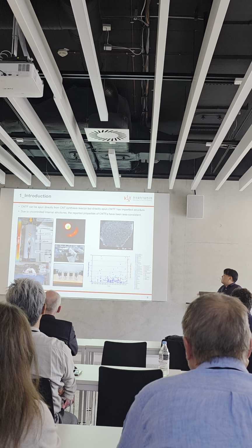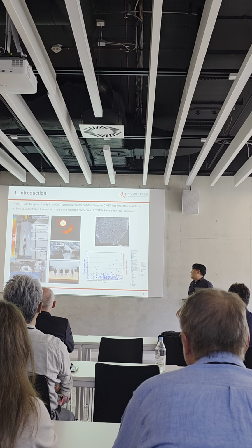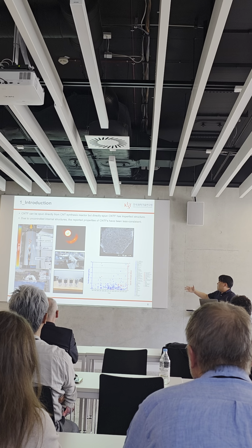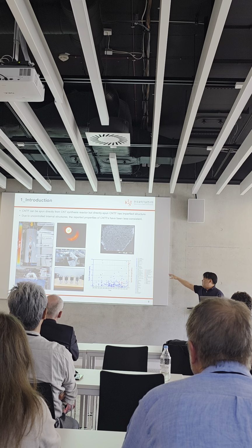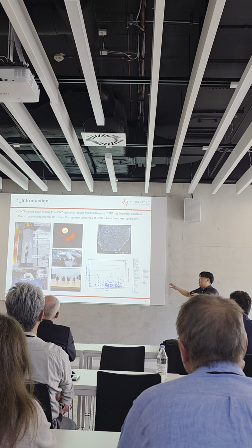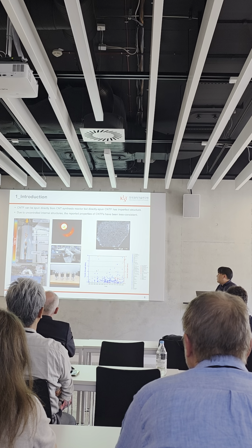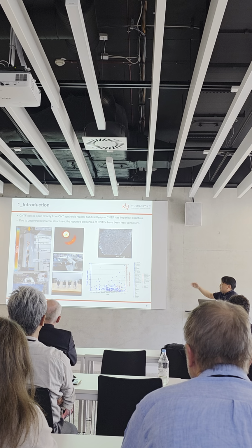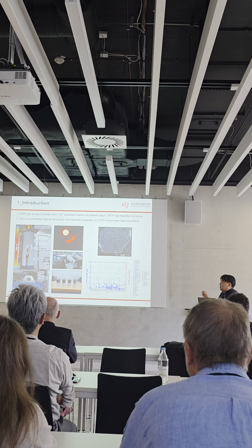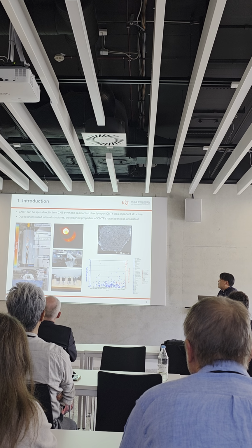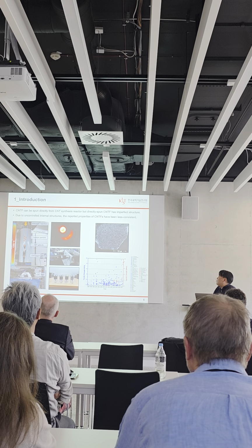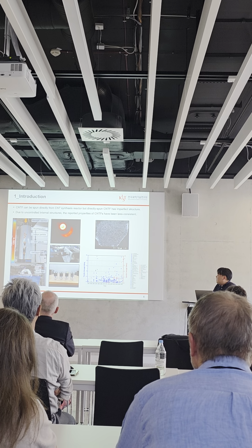We plotted all the properties of direct-spun CNT fiber as of 2017, but they really vary. They fluctuate, so they're not showing consistent results. We think the reason is that the direct-spun fiber has a very poor internal structure with a lot of voids, so it did not produce really consistent results at that time.